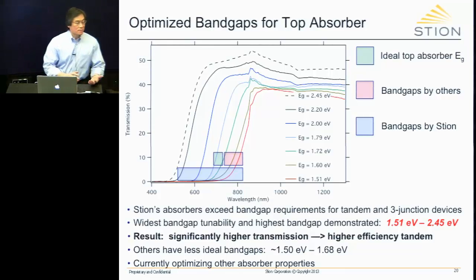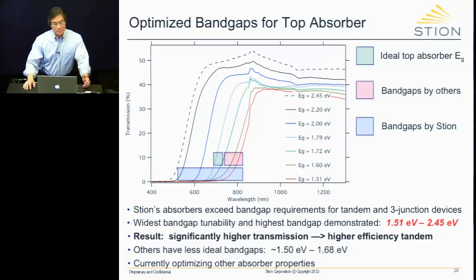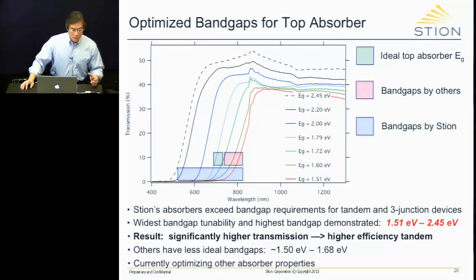And so the problem there has to do with the purity of the material, purity in phase. Oftentimes, if the absorber is not pure, for example if you look at the XRD and you see multiple phases, you oftentimes see that. Sometimes you see Urbach tails that will mess you up. So what's really important is purity of phase to ensure a very sharp cutoff near the band edge. And that's a very good question, because in multi-junction devices, that cutoff needs to be very sharp for reasons that I'm sure you understand. Right?